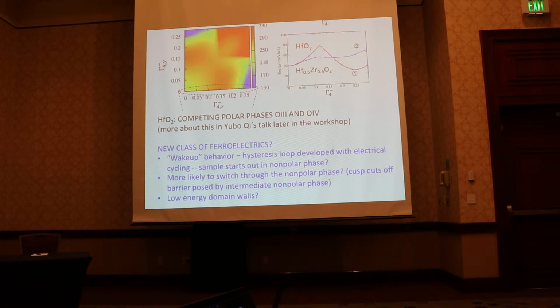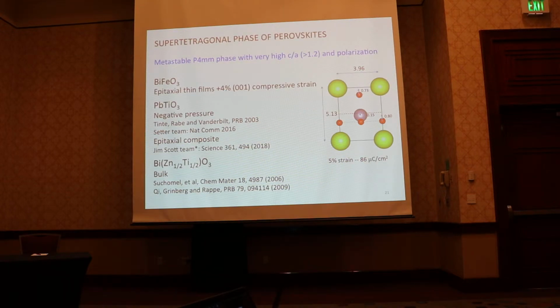It might also have some interesting switching behavior, because again, we don't have the barrier to uniform switching, but you can sort of tunnel into this phase. Similarly, having this very low energy for the nonpolar phase might affect what the domain walls look like, because a lot of times the domain walls are related to the nonpolar, high symmetry version of the polar phase. All right, now